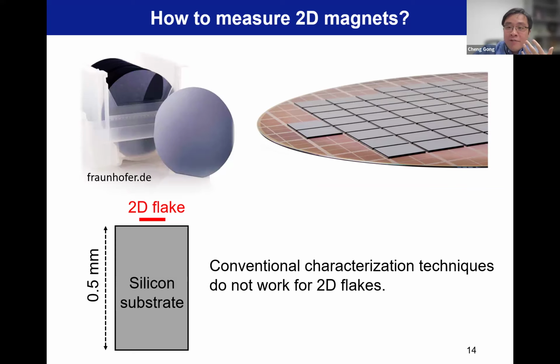So here is a simple illustration for those people who are not in the 2D field. We usually start with a wafer and cut into pieces of chips and then exfoliate the flake. So you can imagine hundreds of different flakes on this chip. But if you only compare this one flake with the substrate, you will find the flake is micrometer size and nanometer thickness, and the chip is millimeter size and half a millimeter in thickness. You simply do a calculation, you will find actually the volume difference is like 10 to 12 orders of magnitude.